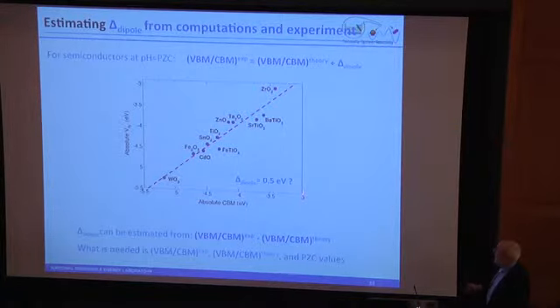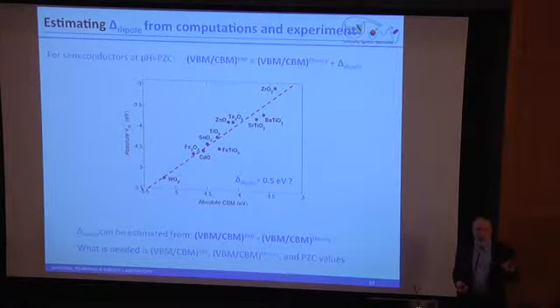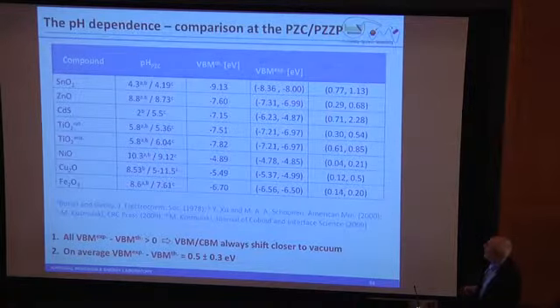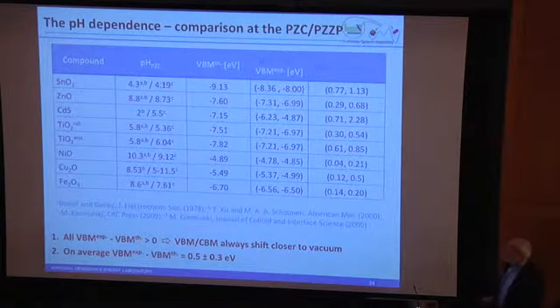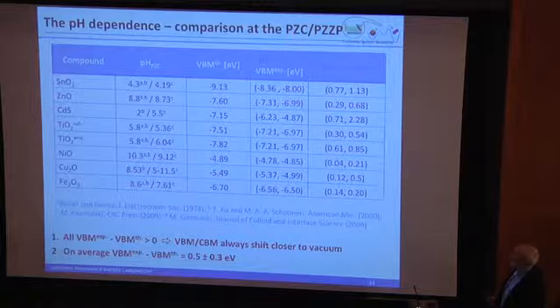So what about this 0.5 eV? Where does that come from? Well, we don't know fully, but what it tells us is that the basic Helmholtz layer, the dipole layer, is basically identical for all these materials, or very close to it. Are there actually other measurements of that? The answer is yes. It turns out that some of the references to the point of zero charge for some of these materials are suspect, so you can throw those out pretty much.